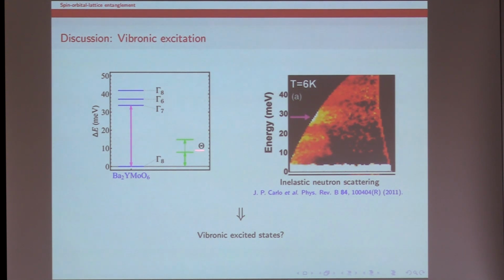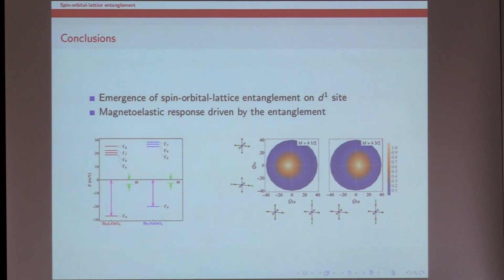And in this system, inelastic neutron scattering has been studied, and there is a strong peak around here. This has been attempted to be interpreted based on exchange interaction, but the experimental Curie-Weiss is around this magnitude, and based on this calculation, I expect this peak may arise from these excited vibronic levels. So this is the conclusion.